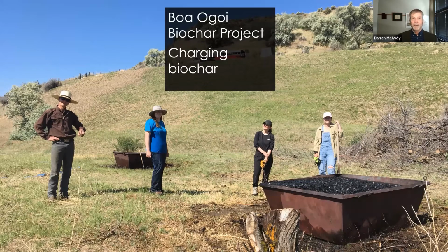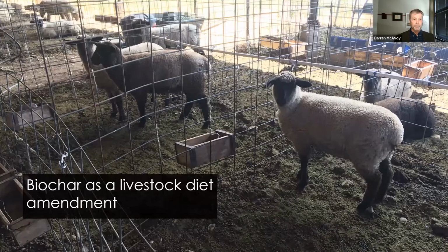Here we made char all morning from Russian olive. We have it quenched, but it turns out this char, I've had it characterized, and it's got a very high pH, about 9.5, something like that. And so we're going to mix it with compost so that settles that down. We can use it as a livestock amendment, a feed amendment, a 2% diet amendment, and sheep actually prefer it. There's some rules against this I can't get into. We're allowed to do it for research purposes, but you can't do it in production methods just yet.